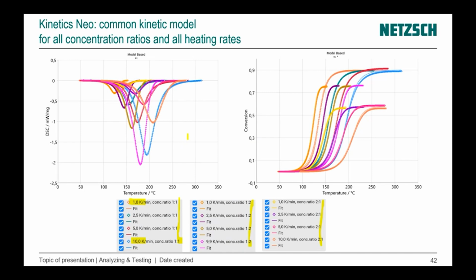That is the first picture, and the second picture shows the peak area, the enthalpy of our reaction, and we can find that the highest is for 1 to 1, where we have almost the optimal ratio of the concentration of both reactants. And if one of them is in excess, then it reacts not completely, and the peak area and enthalpy of reaction are lower than they should be for the optimal value.